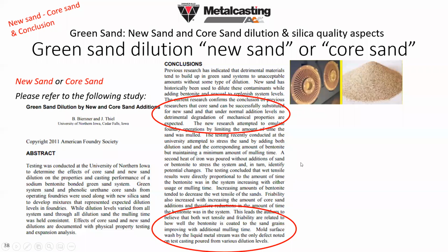However, you can note two points. First, if it is a core sand with much higher resin than MDI, you may not have the same logic of conclusion. And the second point is, for both wet tensile and friability, it is really related to how well the bentonite is coated to the sand grains, and it will be improved by additional milling and mixing time.